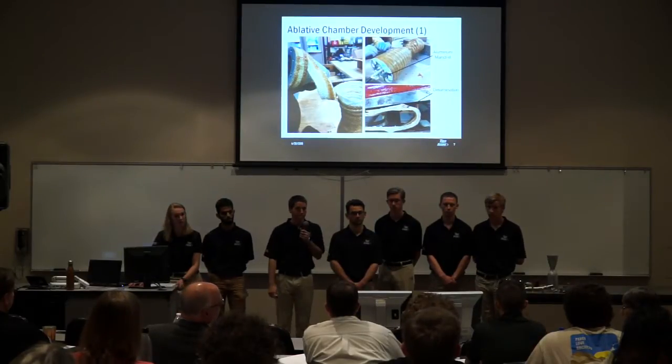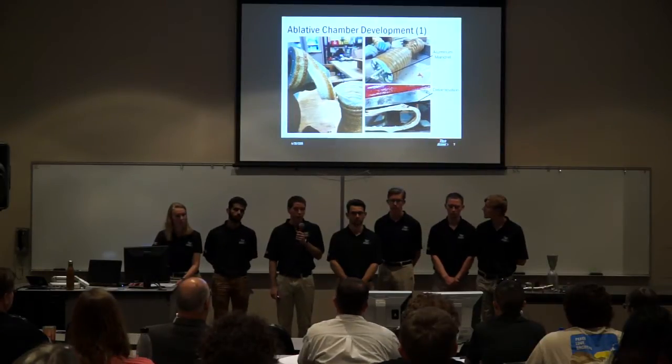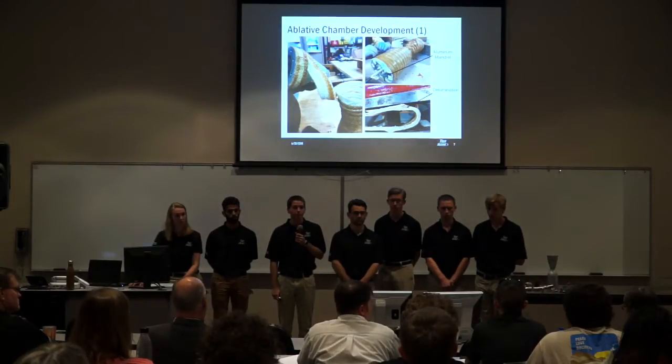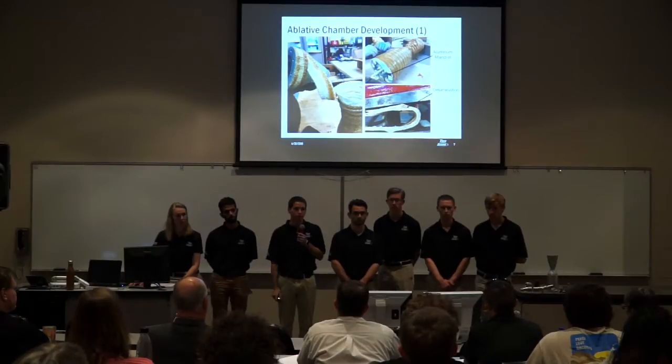So did you envelope bag that prior to putting it in the oven? Yes, it was 24 hours under vacuum, then we pulled it off the vacuum and put it in the oven. 24 hours under ambient or 24 hours at ambient? Yep. That was the resin manufacturer's recommended schedule. Okay.